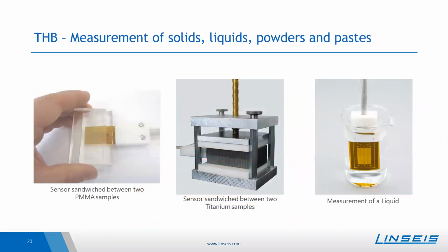So you have already heard that the THB can measure the thermal conductivity of solids, liquids, powders, and pastes. Also, you already heard that the sensor surface needs to be completely covered by the sample, so one needs rather large samples for the analysis with the THB. As already mentioned 2 slides before, typically for solids, the sensor foil is sandwiched in between 2 sample pieces. So it's important that the sample surface is rather smooth so that they fit perfectly on top of each other and there is no air in between those 2 sample pieces.